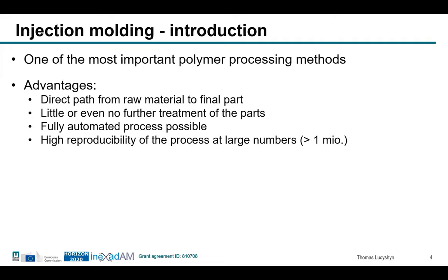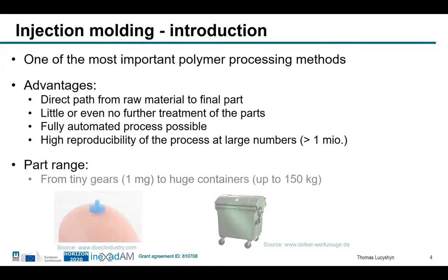So it's totally the contrast to additive manufacturing, where we are typically talking about a few parts. So if you try to produce a few parts only with injection molding, it would be way too expensive. But as soon as you're going to higher numbers, then it's economically feasible. The part size is ranging from very small parts, from tiny gears in the range of like 1 milligram up to huge containers up to 150 kilograms.